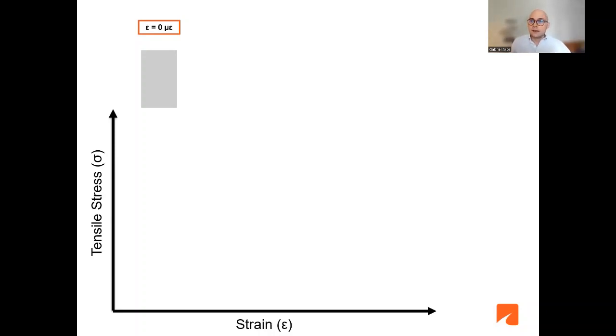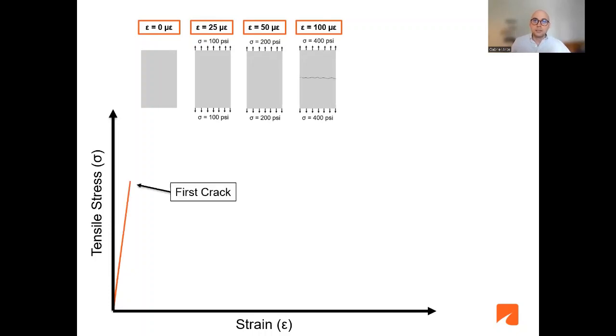At the beginning, no strain, 0 microstrain, nothing's happening. You continue deforming the material, 25 microstrain, the stress response is about 100 psi. You continue until suddenly, when you reach about 100 microstrain, which would produce about 400 psi of tensile stress in the concrete, the conventional concrete would crack.